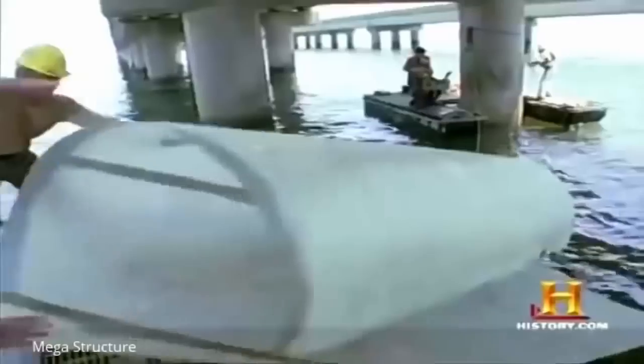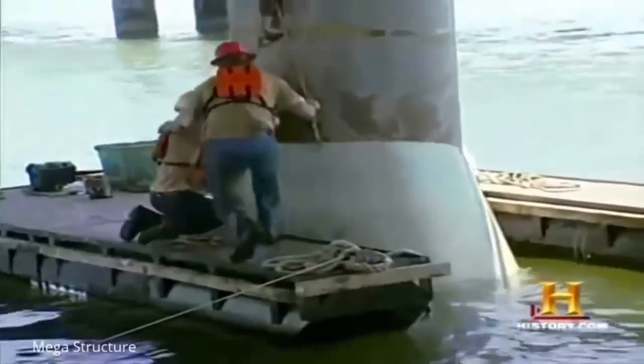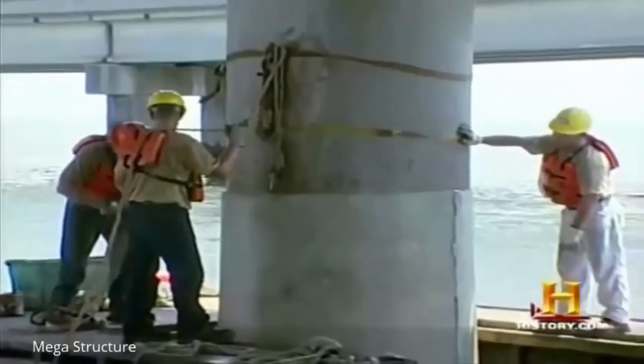The lake is brackish water, and the brackish water attacks concrete. The sulfides in there attack the cement, and you do get some erosion, particularly at the wash line. We inspect those to see what repairs need to be made, such as hairline cracks that are repaired by epoxy repairs of those cracks. Some of the more severely damaged piling are totally encapsulated with a fiberglass collar.